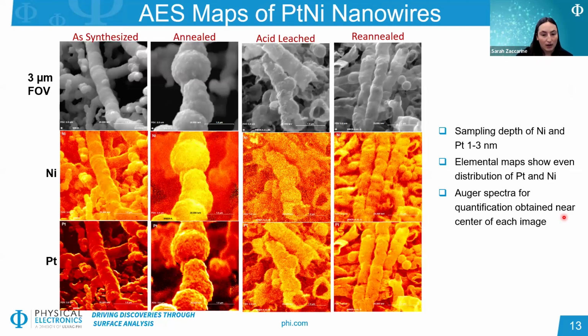So next we used Auger spectroscopy to map the nickel and platinum distribution for these 4 different samples and compare this to the SEM images on the top. So the sampling depth of nickel and platinum with this technique is about 1 to 3 nanometers. So again, the fact that we're seeing nickel means either we're probing through the platinum layer and or we might have movement of the different metals happening with these different treatment steps. We see generally a pretty even distribution of platinum and nickel. There are again a few different wires present. We see this nice morphology present, but generally they're fairly uniform.